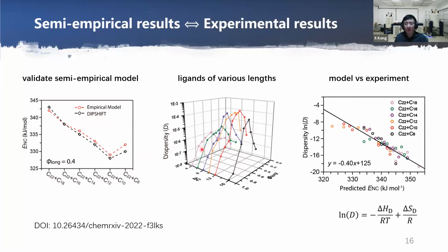Then we can use this model to calculate the interactions of samples with different ligand lengths and ratios. Here, there are no NMR experiments performed. We just use this semi-empirical model itself. So the calculated interaction energy follows the expected thermodynamic equation for the solution dispersity. This demonstrates the general applicability of the dynamic volume concept. I think in principle, this concept can be extended to other types of ligands and also other structures with flexible components. And if you are interested, you can refer to this manuscript that we just submitted.